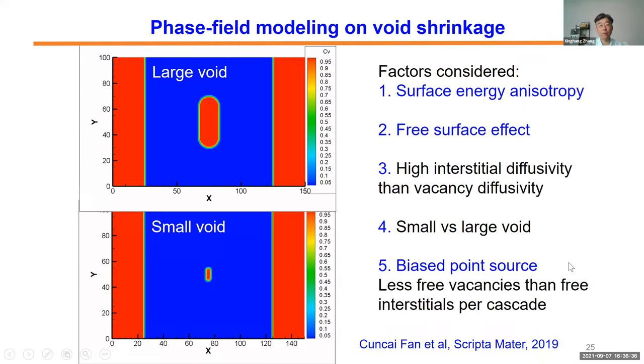So then we collaborated with Professor Anter, who was at Purdue. He's a phase field simulation expert. So he asked his student to set up two models in pure copper. In one case, there's a relatively large void, and in the other case, very tiny voids. The aspect ratio is about the same. And the color code: red means vacancy concentration, and because this is a vacuum, this is really dark red. And blue means vacancy depleted. And this void is right in the center of the copper, so it is also colored in red.